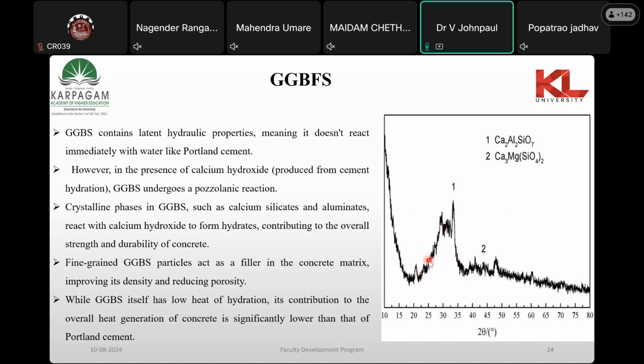like fly ash. In the crystalline phase, calcium silicate and alumina react with calcium hydroxide to form hydrates. This is what will go through during the hydration process in the cement, contributing overall to the strength and durability of the concrete. Fine-grained GGBS particles improve its density. While GGBS itself has a low heat of hydration, its contribution to the overall heat generation of concrete is significantly lower than that of Portland cement.